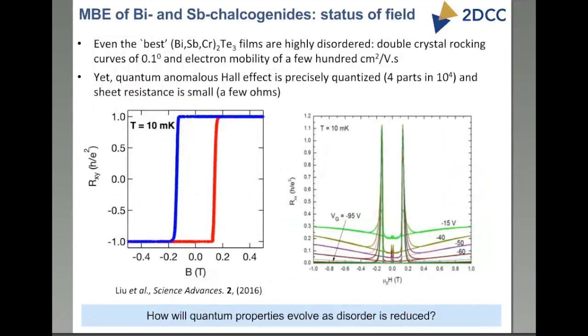Now, remarkably, and this is data from my group in a collaboration with a group at Princeton, we've shown that even though the best bismuth antimony chromium telluride films are highly, highly disordered, the best double crystal rocking curve widths are about a tenth of a degree, and the mobility of the electrons is only a few hundred centimeters squared per volt second.